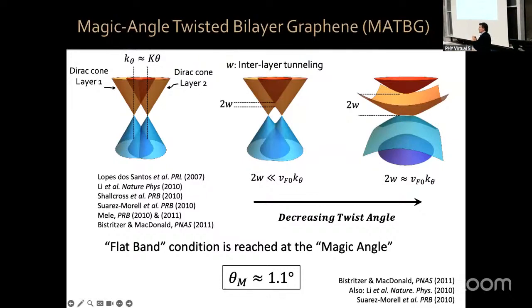For the experts, it's called the van Hove singularity. It's a peak in the density of states that can be picked up by scanning tunneling microscopy. This group showed that peak going to low energies, extrapolating to zero at about 1.1 degree. This behavior, which is all single particle physics, was relatively understood about 15 years ago.